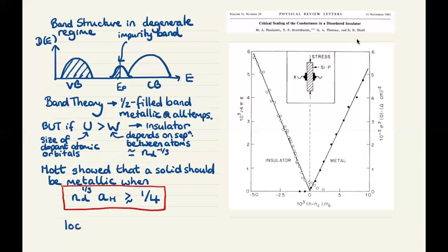Okay, so let's have a look at some data. And I want to look specifically at two examples. So here's our first example. And in the first example, we're going to keep the hydrogenic radius constant. This is an experiment which is done for a sample of phosphorus in silicon at a single doping concentration. And so if the hydrogenic radius is constant, then the Coulomb repulsion is approximately constant also.